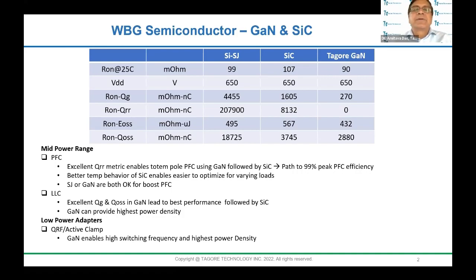Next metric is QRR. The QRR of superjunction is very bad, as you can see, and there are some versions of superjunction where the QRR is a little bit better than what I have quoted here, but for continuity, I kept the same device. Here we see silicon carbide is significantly better in QRR, the reverse recovery charge, whereas in GaN there is no reverse recovery charge; it is close to zero. The next metric is EOSS, and surprisingly, because of the way the superjunction is architected, the EOSS is pretty good and fairly comparable to GaN and silicon carbide. All three are approximately the same.